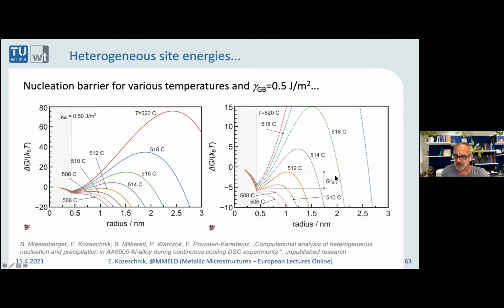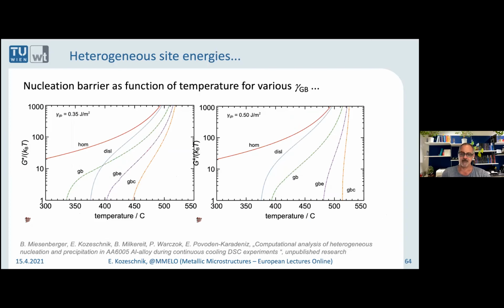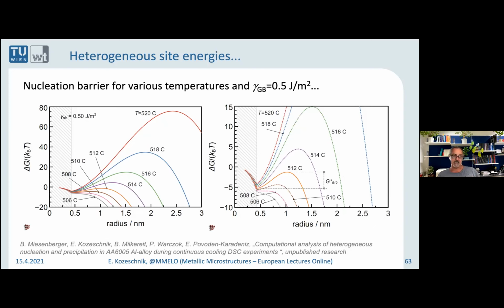So this is the G star for 512. Even if all the values are negative, you have to count this barrier here. But if you go to 508, you will find that the barrier will totally or completely disappear. And that is something that solved the problem of how nucleation of this phase can occur, even in very slow cooling, in very low supersaturation regime.